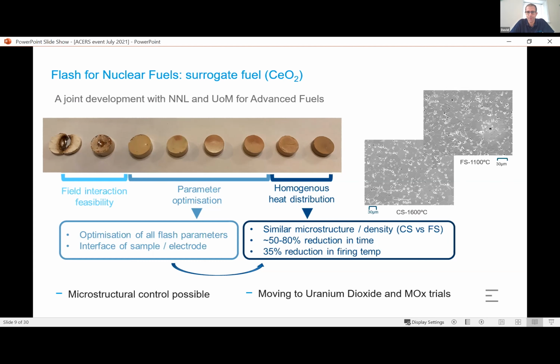Typical over kind of a 5-month process, you go from blowing holes in the sample where you can see the melted middles, and then you start to find the field parameters that work, and then you actually start to get homogeneous sintering or in-field interaction that's not localizing, but you're still not sintering the whole pellet, all the way through to the far right now, where we're reliably churning out these fuel pellets on surrogate fuels without any cracking, without any stress induced there, and hopefully homogeneous.